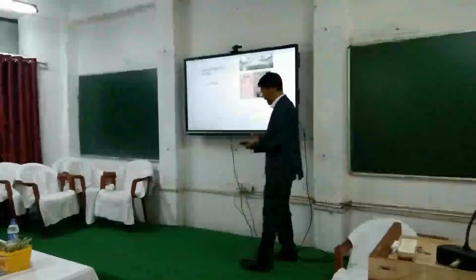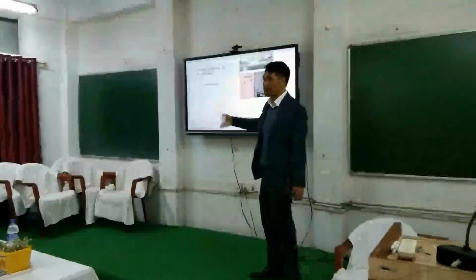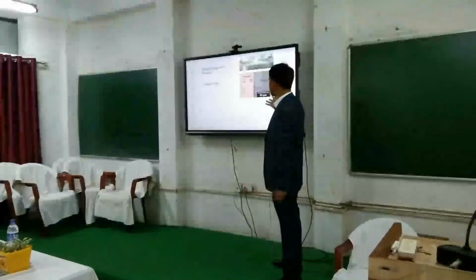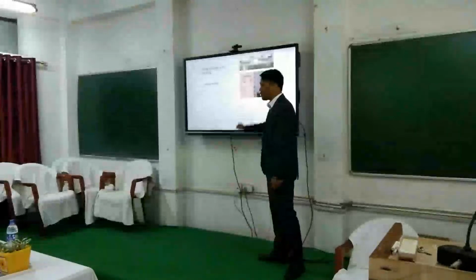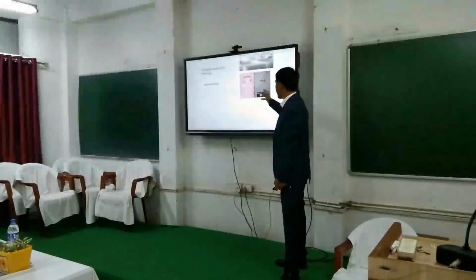So those were for low temperature alloys like aluminum, magnesium. High temperature alloys like stainless steel and copper, which have a melting point above 1000, also can be joined by microwave heating. Here we have used copper itself as an interlayer. This is copper powder, and we have got the joint between stainless steel and copper.